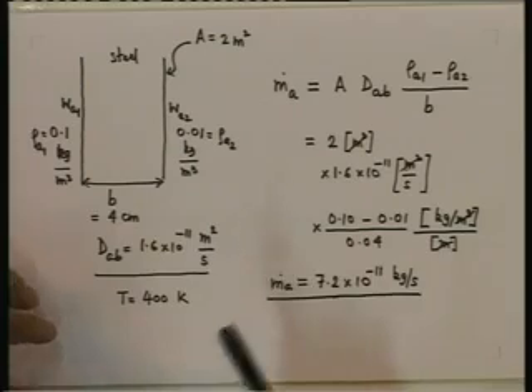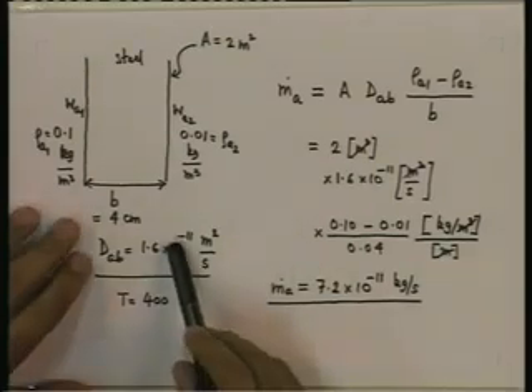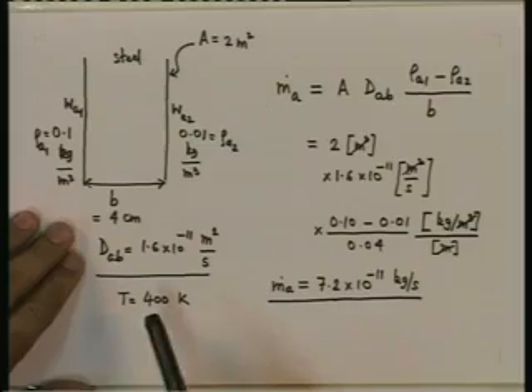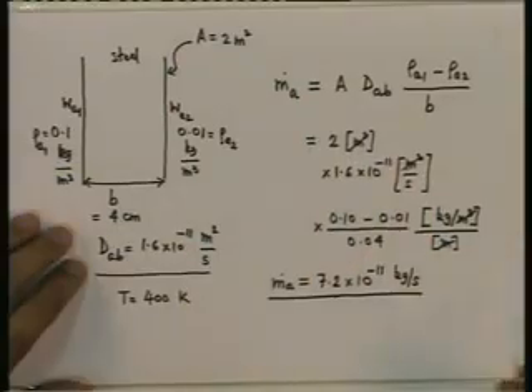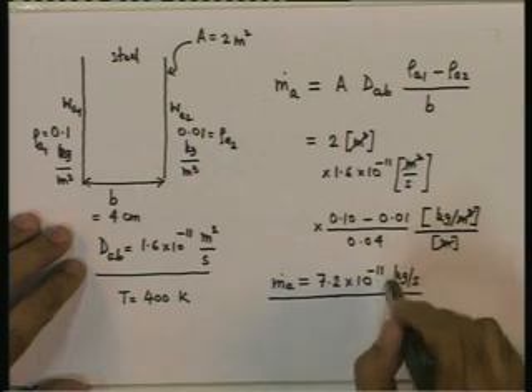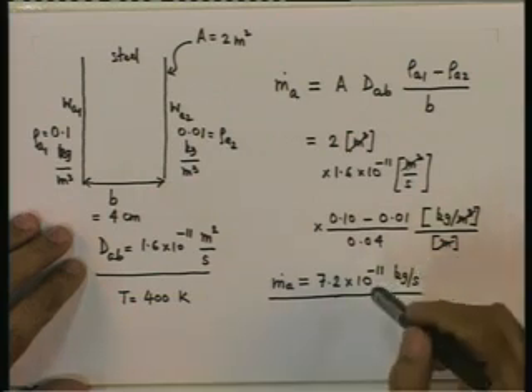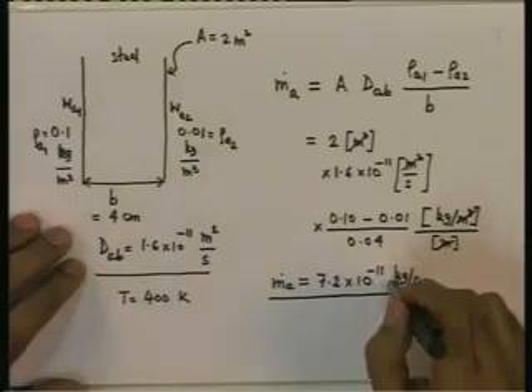Now, notice that the diffusion coefficient is a significant function of temperature. If the temperature increases from say 400 to say 1200 Kelvin, 3 times, the diffusion coefficient will go up not just 3 times, but not even by the square of 3 times, 9 times. Maybe it will go up by a factor of 5 or 6, and that means even the diffusion rate, or if you want to call it the leakage rate of hydrogen through the slab, will also increase. This indicates that at higher temperature the chances of hydrogen embrittlement are large.